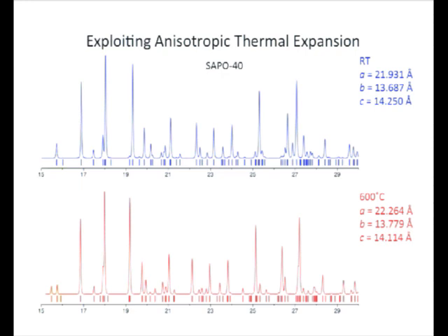If we look at another section, here we have overlapping reflections and quite a strong peak. If we equally partition this, we would get it really wrong, because it's actually a very weak peak next to a very strong peak. So with just these two measurements, you can get a lot more information about the relative intensities of your overlapping reflections. This is a much more severe treatment than Kenneth was talking about. That was for organics. Just a gentle heat treatment will change the lattice parameters enough so that you can play this kind of game with a relatively simple experiment.